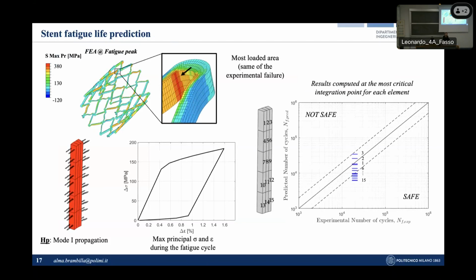Also, in this case, we were able to obtain promising fatigue life predictions for the stents, where here each one of the horizontal lines represents the prediction for one of the 15 elements. And the prediction is compared to the experimental range of number of cycles to failure, considering the 3 tested devices. Also, in this case, we have a perfect match in correspondence of the solid line, while we have a conservative prediction below the solid line.